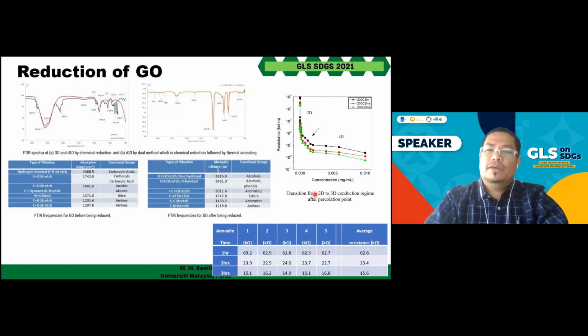So what we believe, this is a point where we reach the percolation region or percolation conductivity. Starting from here up until here, at a concentration less than 0.05 milligram per milliliter, which is a very, very small amount of reduced graphene oxide, we believe that this regime is a 2D regime where the resistance is quite high.